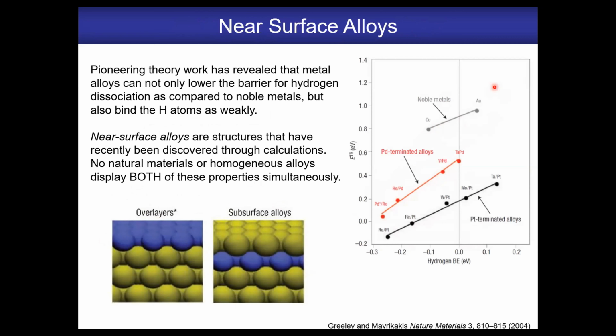And what Manos is plotting here is, the line here is for the single 1-1-1 surfaces of the noble metals, where you have a correlation between the binding strength of hydrogen atoms on the surface, more strongly bound this way, and a lowering of the transition state energy for activating the molecular hydrogen. And what he's plotted here is that for a lot of these near surface alloy combinations, you can dramatically reduce your activation energy for dissociating molecular hydrogen, but also keep the weak binding of the hydrogen atoms on the surface, so you can get both things that you want. And that's a very exciting result.